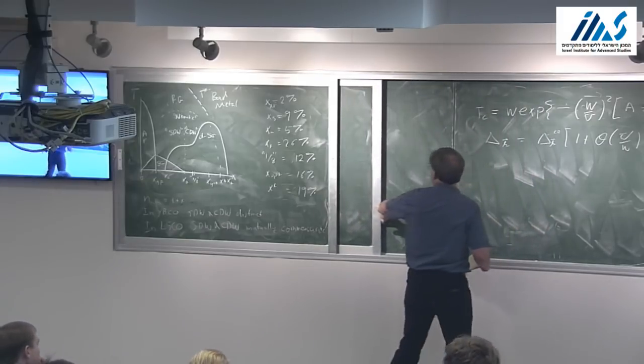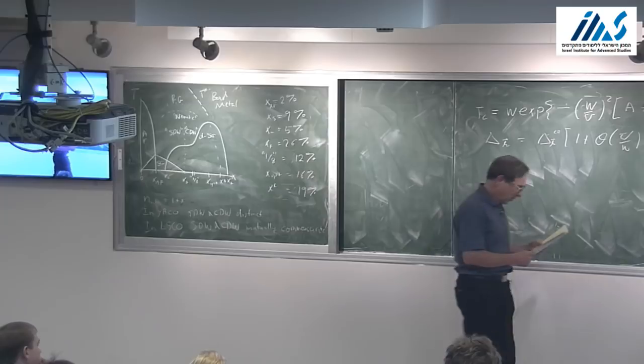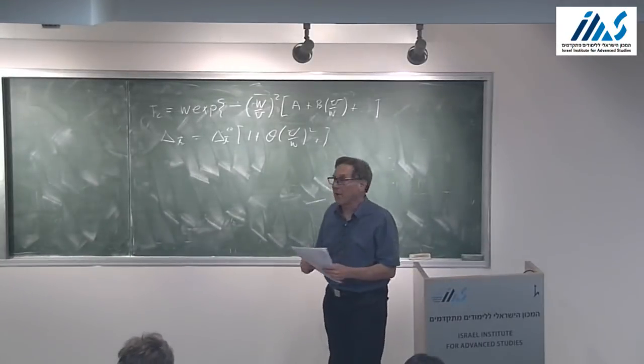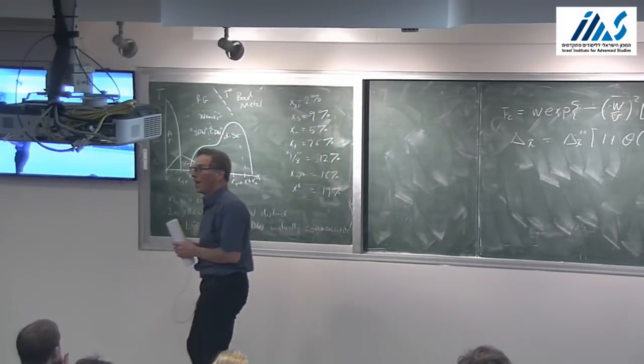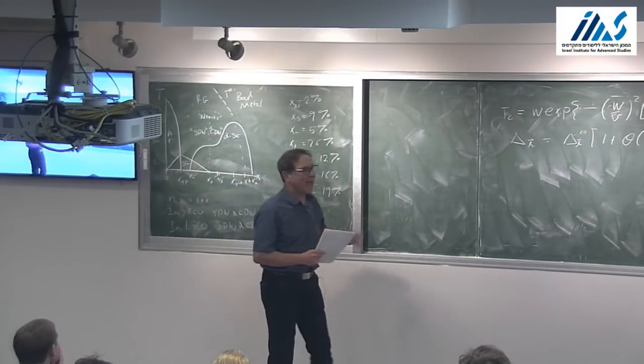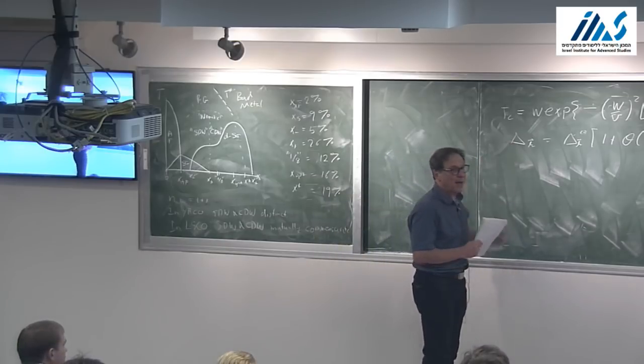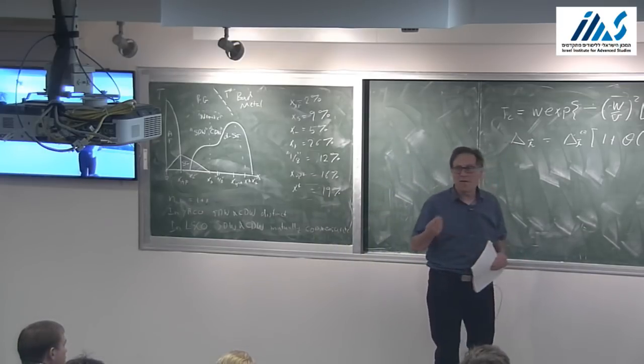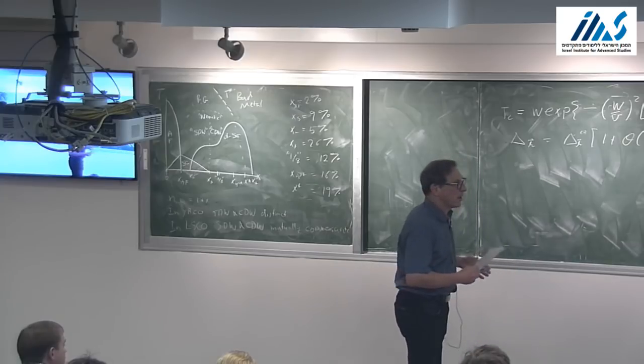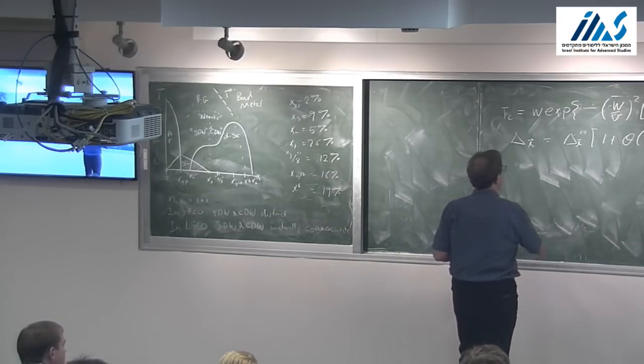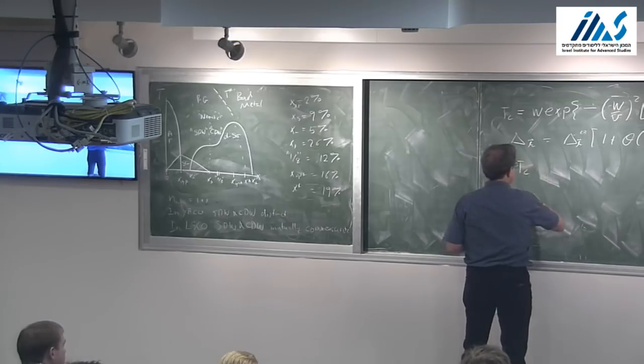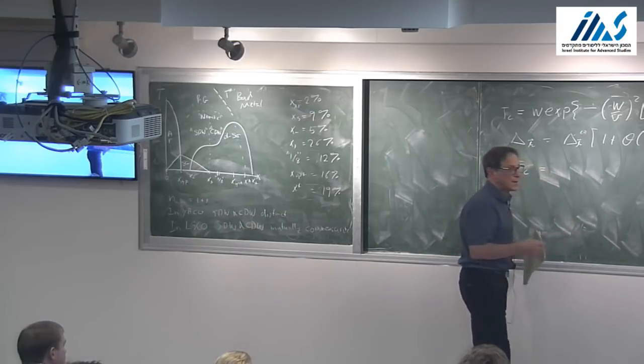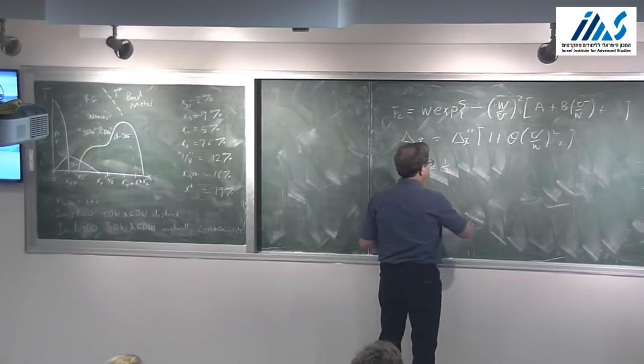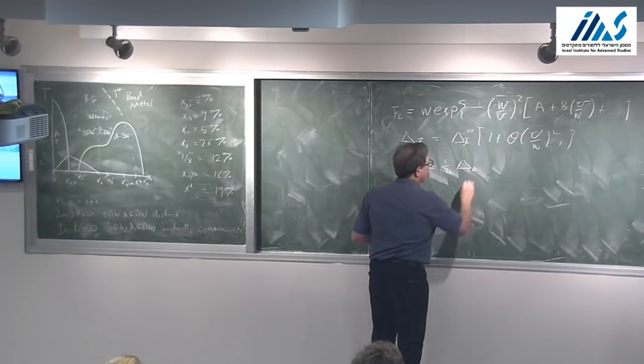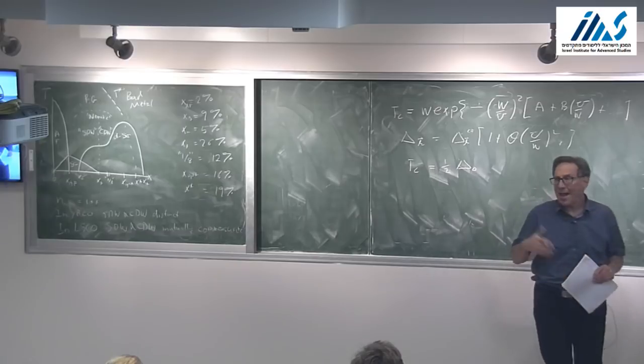But there's an even more important thing that we don't understand about the superconducting state, and that's the following. There are really two new features that characterize the superconducting state. One is the gap, and I've just talked about that. And within any sort of BCS-like mean field theory, and certainly within the weak coupling theory here, what one finds is that TC is going to be equal to some number, typically around 1/2, times the gap magnitude. And that tells you something.